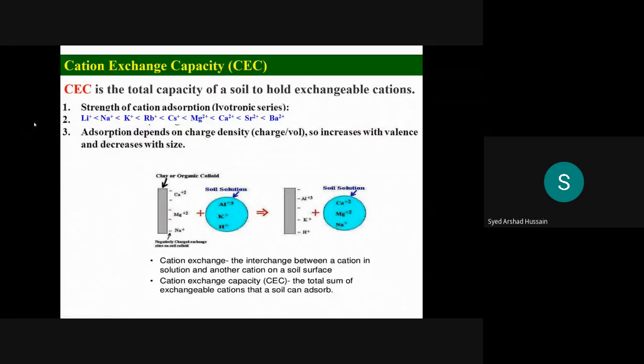And it depends on the absorption capability. This is the cations existing in between the clay layer or on the surface. And there is an order, that is a rate of adsorption, and this is called lyotropic series. And this cation exchange is mainly the interchange between a cation in the solution, that is what type of cation you want to incorporate in the clay, and another cation in the soil surface. So one can incorporate or place desired types of cations onto or in between the clay layer.